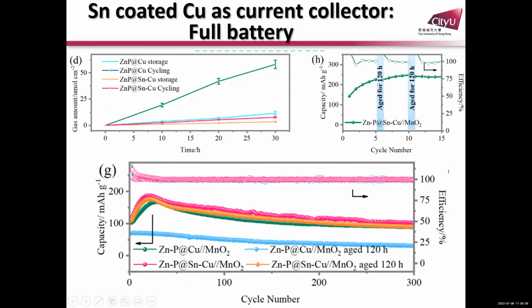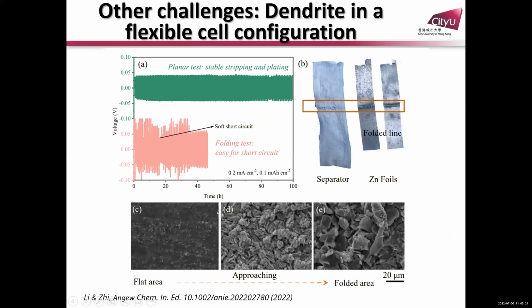And also, even after a certain amount of time, for example, 120 hours of storage, the stability of the capacity is much better. And this is also without coating. This blue one, after storage, is much worse. But if you coat with tin, it can be improved a lot, although it's not 100% solved.